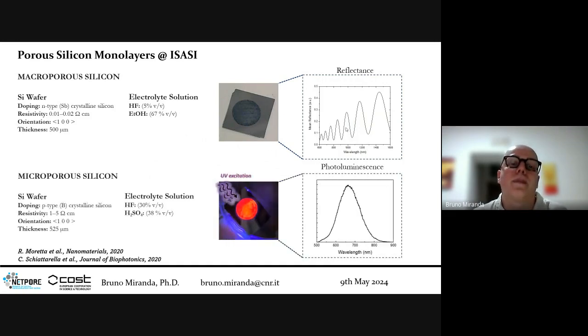The two types of structures that we create are these ones. Basically, this is a porous silicon monolayer, macroporous silicon, that we obtain with these conditions, and this is the typical reflectance spectrum that we can both predict and measure with optical setups.